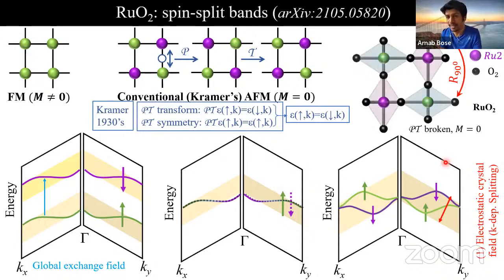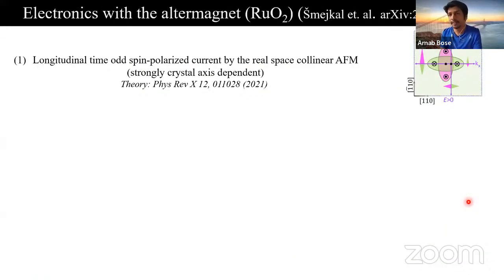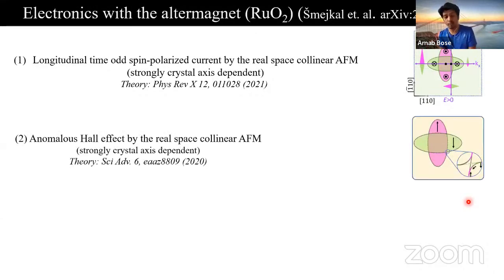So it is a real antiferromagnet in real space, and however, it exhibits spin split bands like a ferromagnet in momentum space. That's why it has been referred to as a new class of material called altermagnet. And we'll see from the predictions that these spin split bands will have tremendous influence on the electronic transport properties. For example, depending on the direction of the applied current with respect to the crystal axis, we can get the behavior of a ferromagnet from this altermagnet. For example, it can exhibit longitudinal spin polarized current and anomalous Hall effect, and so on.